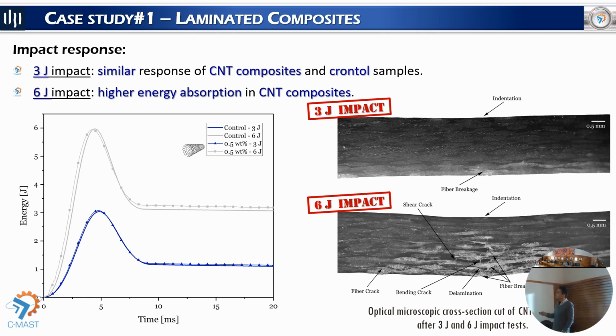These two microscopic images are interesting to show what I mentioned in the beginning of the presentation. Here we can see what happens in the composite structure in an impact event. Here in this zone impacted by the object, we can see the presence of an indentation, but the damage that occurred inside is not visible here. And in this case of the 6 Joule impact, we see, of course, the indentation, but on the opposite side of the composite, we can see that big damage occurred.